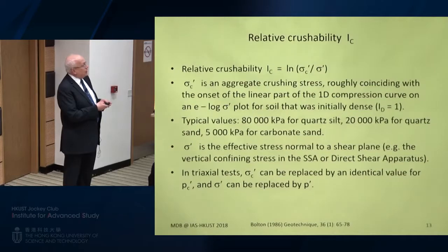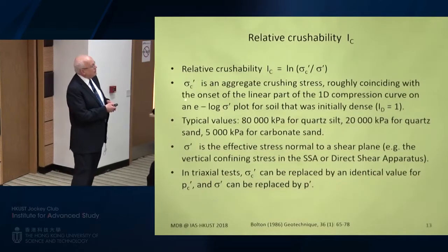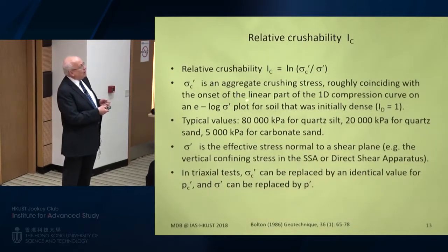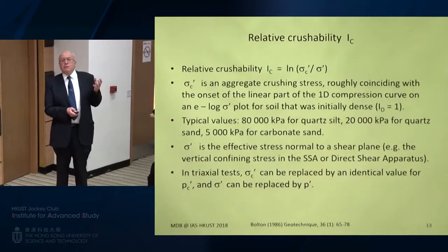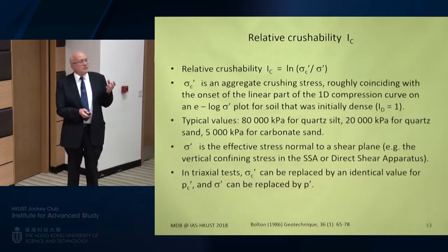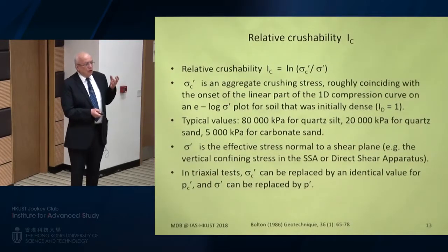So, crushing. So sigma dash C is some parameter, maybe as I've described it, but to be determined perhaps by shear testing, looking at how the dilatancy is wiped out at enhanced stresses. So typical values, in the 86 paper I talked about 20 megapascals for all quartz sands. That must be a gross simplification because I know there's a size effect. Large grains are weaker in proportion than small grains.